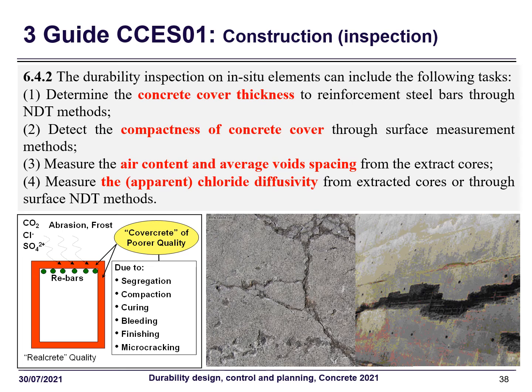The reason for this is, whether we use a durability indicator or not, they are all parameters based on laboratory tests. The real quality indicators, the most pertinent indicators, are to be measured directly on the surface of the finished members. That's the idea. So in that sense, we need to make the inspection of the durability quality of the hardened concrete members. So in this article, we just set up some basic rules to make this kind of inspection. For example, to measure the concrete cover thickness, compactness, air content, average void spacing, and some transport properties.